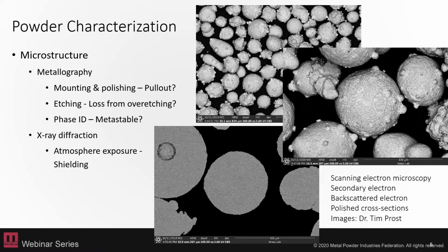And images like SEM can help you identify those features and keep that as part of your quality control. Also, X-ray diffraction is a common metallurgical method to look at your phase identification. But again, maybe you're exposing your powders to the atmosphere during that process. Maybe you're only getting the metastable phases that are present in the powders. And so you need to keep that in mind and maybe shield your powders, or maybe age your powders in a furnace or something like that, that might be relevant to the exact composition that you have.